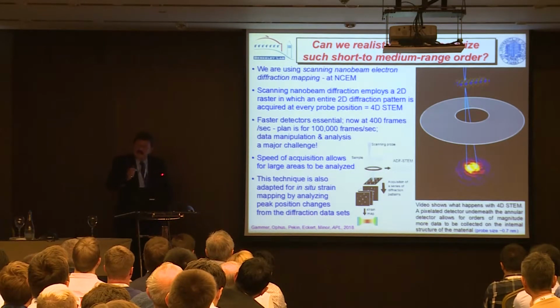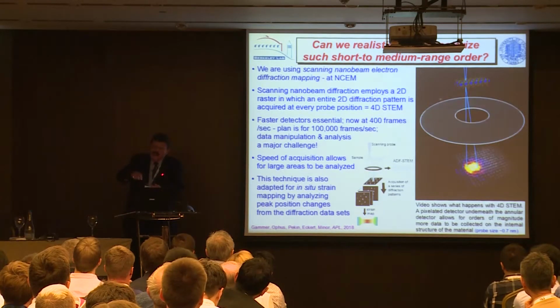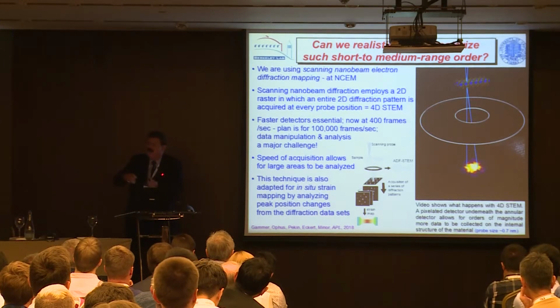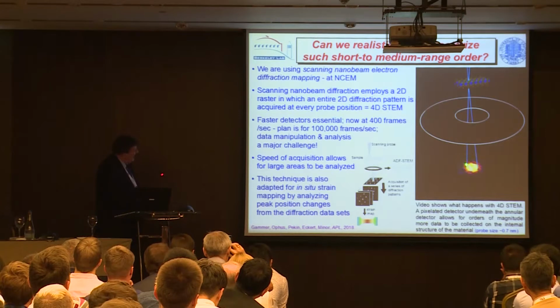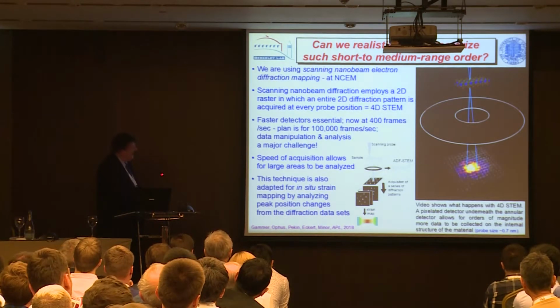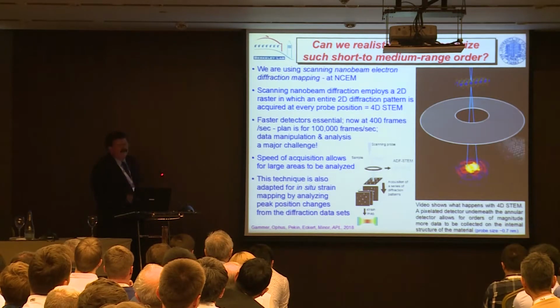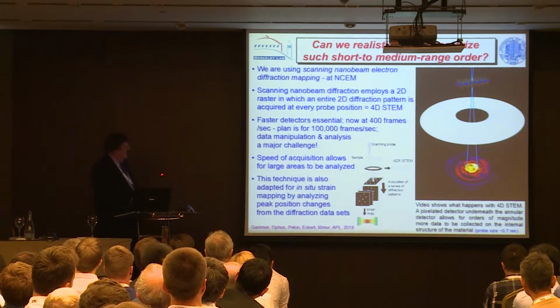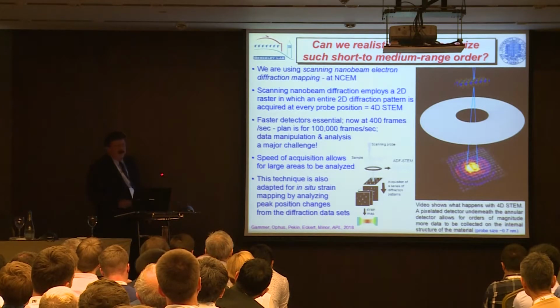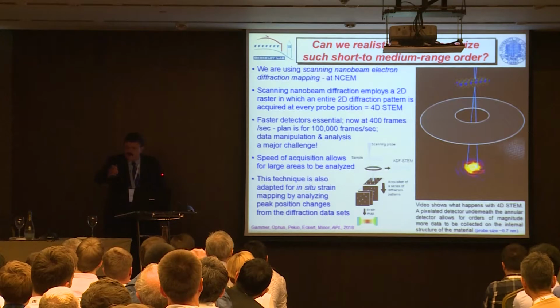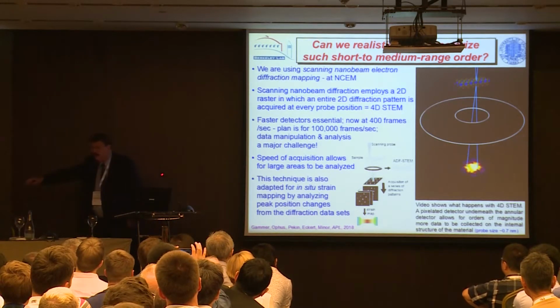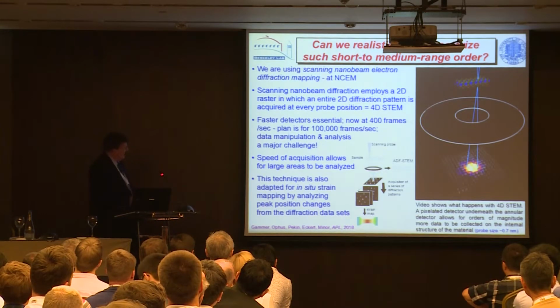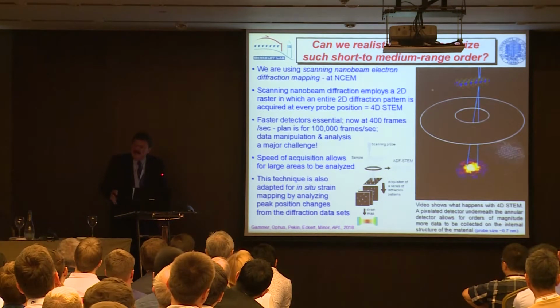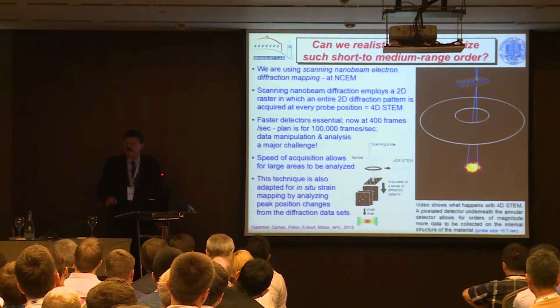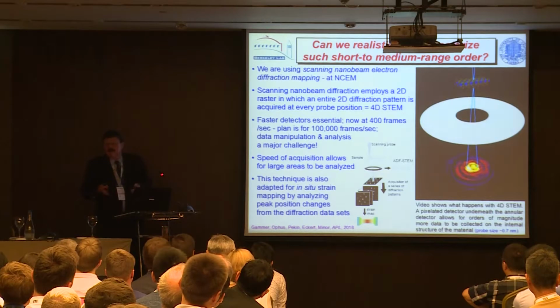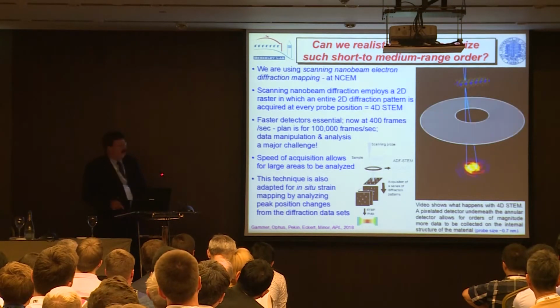Basically, we scan small regions. They're about a nanometer square region, a little column, about 50 atoms in each little column. And that's sort of short to medium range order. And we take a diffraction pattern and we move on and we start moving through the structure. But we can do this extremely rapidly. We have extremely fast detectors on our TEMs now, which can look at 400 frames a second. And within the next year, we'll be up to 100,000 frames a second. So we can look at these little small regions, map out the order if it's there, and then move through large areas of material. We can also, at the same time, measure the local strain. So we can get the icosahedral symmetry and the strains for each region at the same time. So there's a chance here we might be able to put two and two together and show that these GUMs are the essence of plasticity and toughness of these glasses.